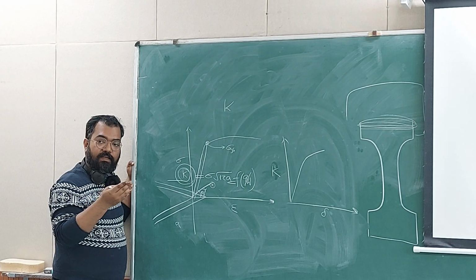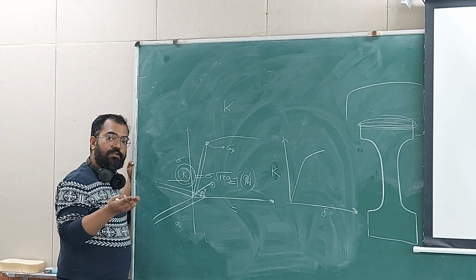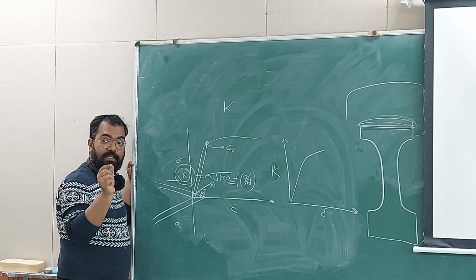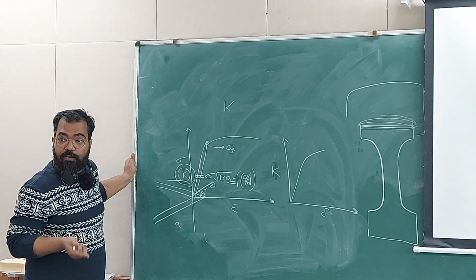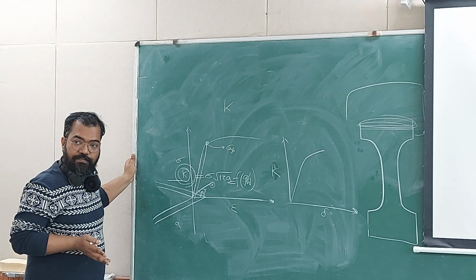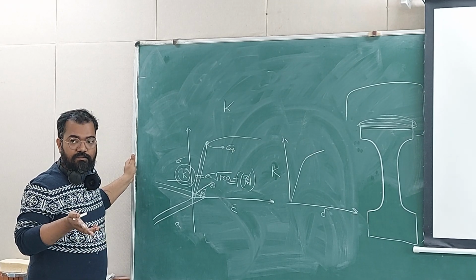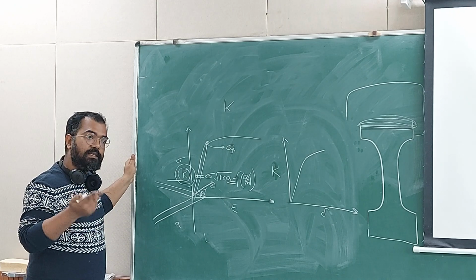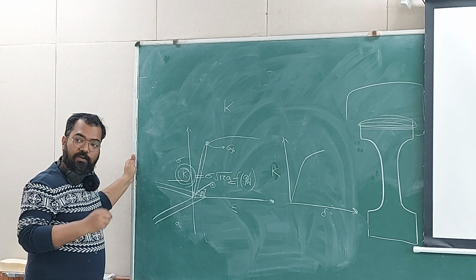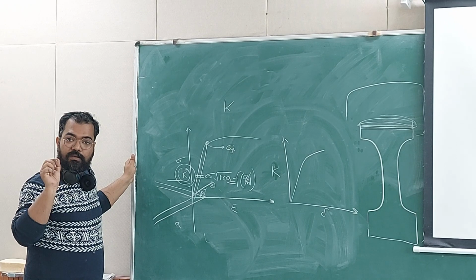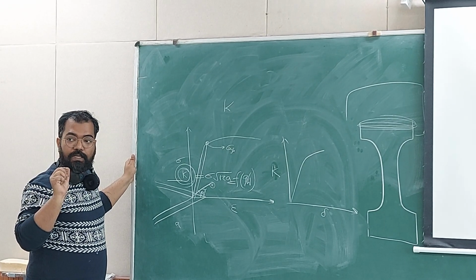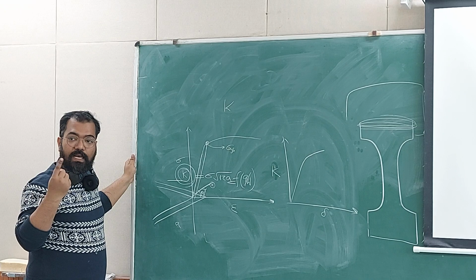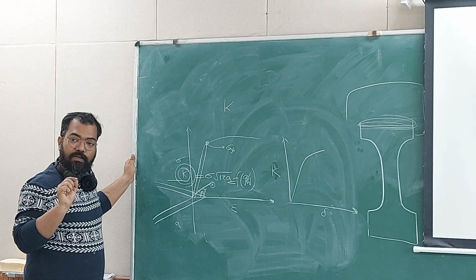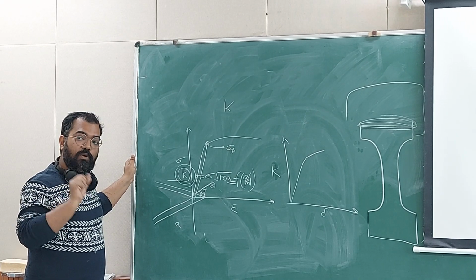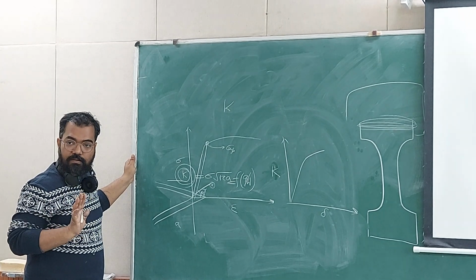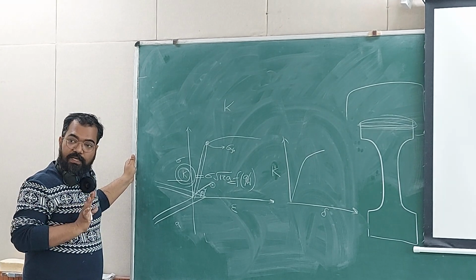If you have a stress condition or crack condition such that K is smaller than that critical value, then the crack will not propagate in that material. So if I take AISI 304 steel, mild steel, titanium alloy, all of them have their own critical value. If you cross this value, the crack will propagate and you can't stop it. And if you are lower than this value, the crack will not propagate. So this can help in design criteria.